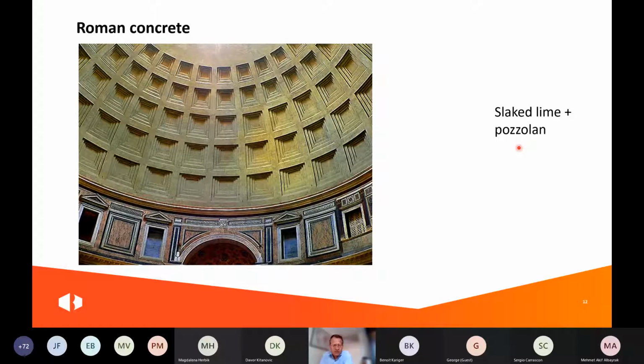The Romans improved this lime by adding a pozzolan. This pozzolan could be ash of volcanoes found in the neighborhood, in Pozzuoli around Vesuvius. But they could also use ground tiles as a pozzolan, and this pozzolan takes the lime from the burnt lime and can react with it and form CSH gel. That's the main component also in modern cement stone.